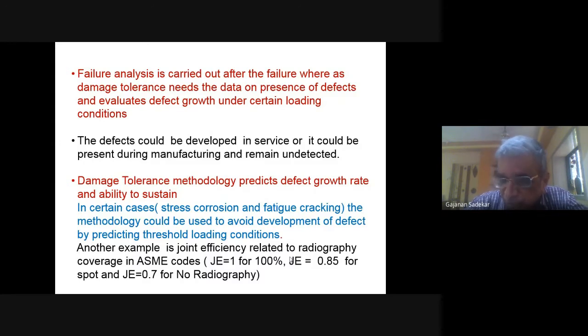Now imagine what happens when you do the 100% radiography also. ASME doesn't say zero defect. There are small cracks, and a limit is given for how we can accept the radiographs. So that permits something. This means there are some damages, defects available in the joint, right? Then it says joint efficiency, if it is spot radiography, this means you are going to check only 10% of the weld by radiography. In that case, you have to take the joint efficiency of 0.85. And if you are not going to do any radiography, then the joint efficiency is 0.7.